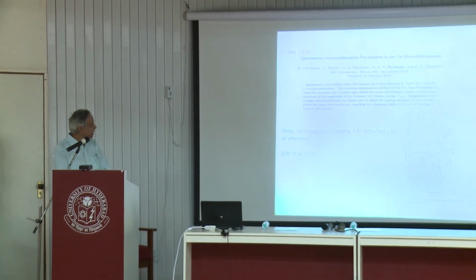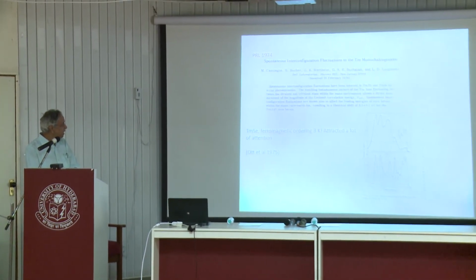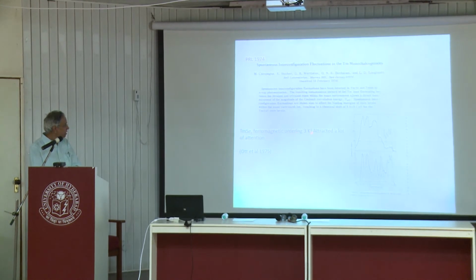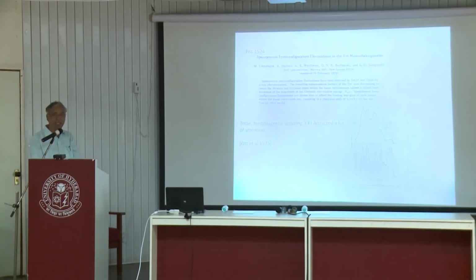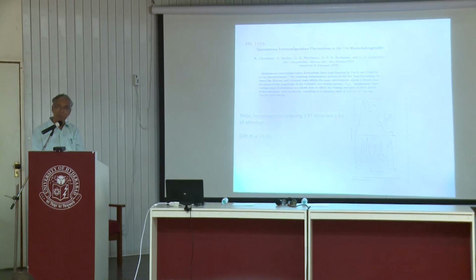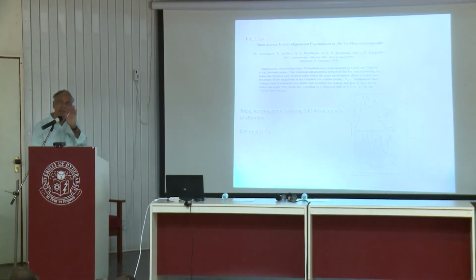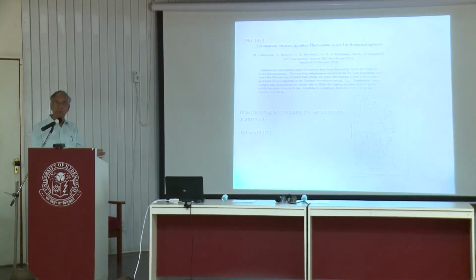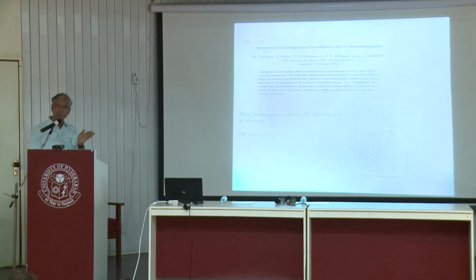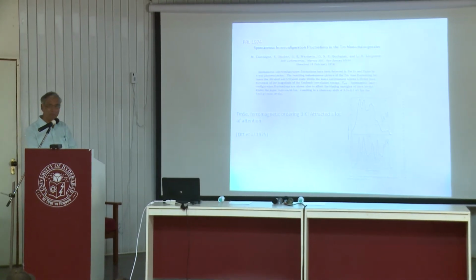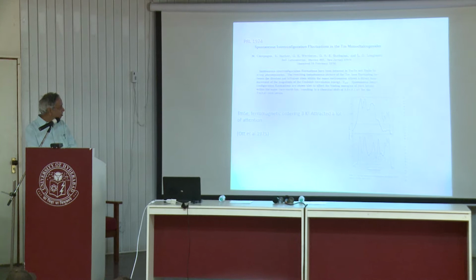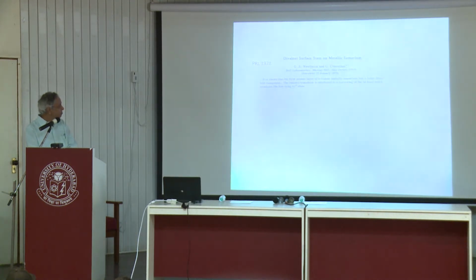Let me skip that without confusing you, but I should mention that in this system, thulium selenide, the same problem happened, but the problem here is that thulium selenide turned out to be magnetic. Here also your electron goes out and comes back in the same time scale, but this created a lot of confusion. Why is it ordered magnetically at low temperature?